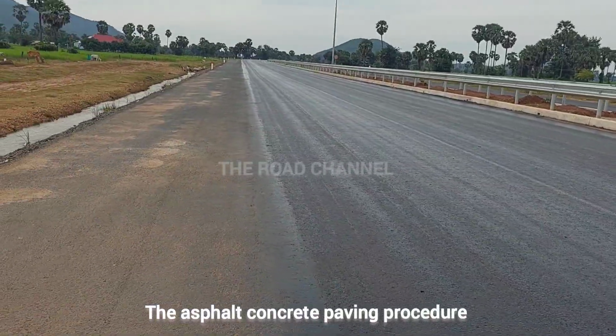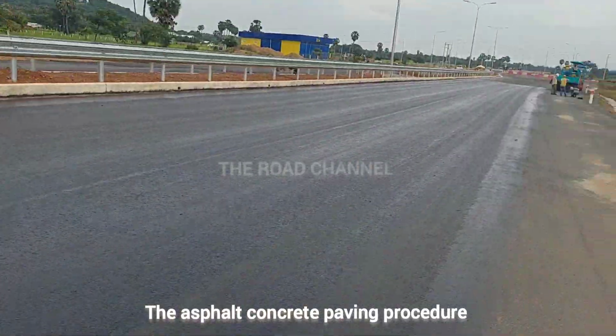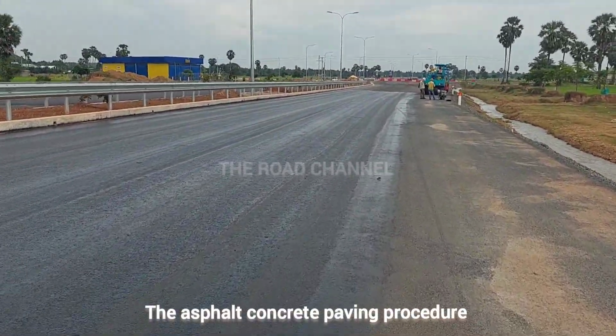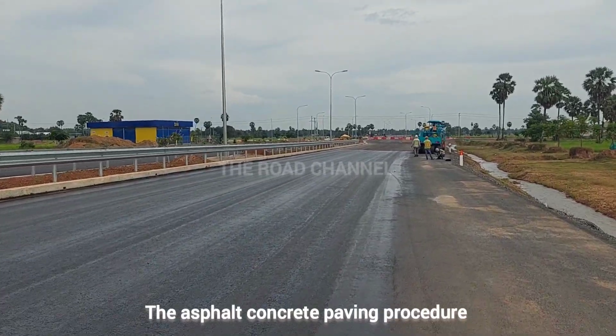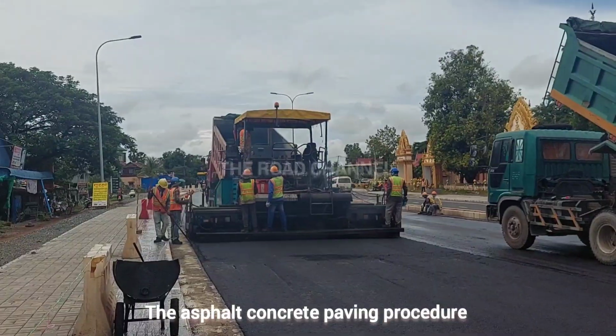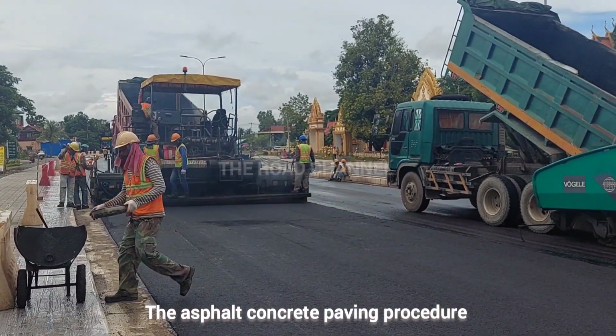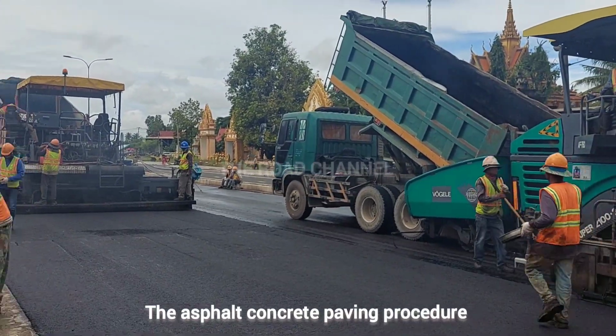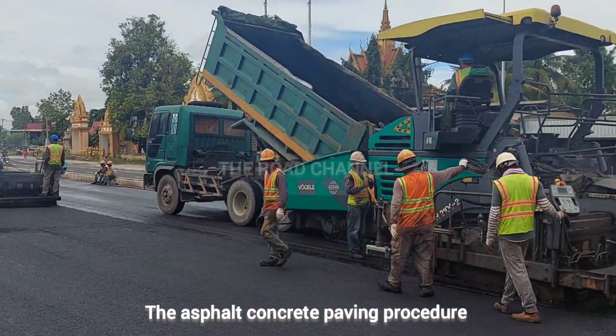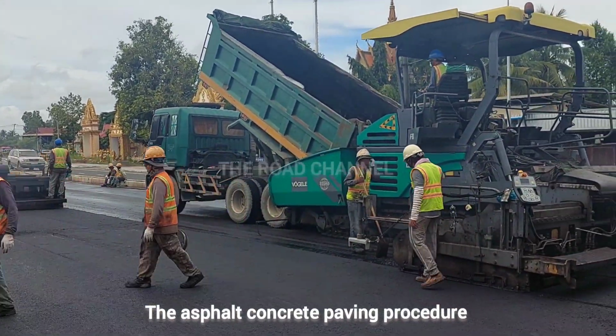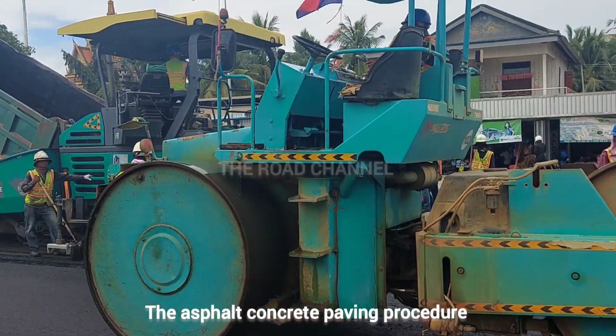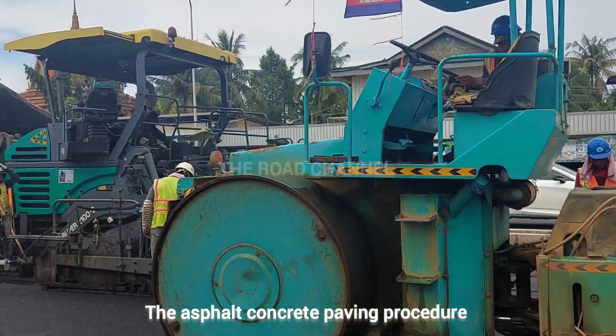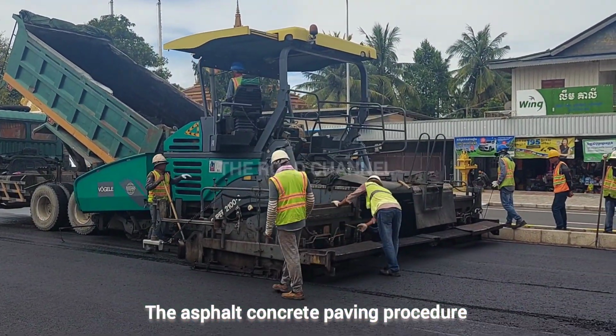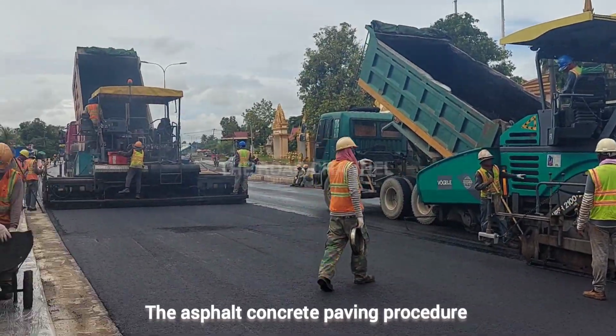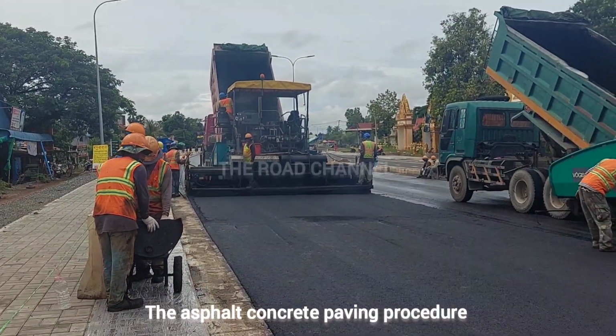3. Paving process. Spreading the mix. Use an asphalt paver to spread the binder course mix evenly over the prepared surface. Thickness control. Ensure the laid thickness meets design specifications, typically 50 mm to 100 mm, depending on traffic load. Temperature control. Maintain the required temperature, usually 140 to 160 degrees Celsius, to allow proper compaction.